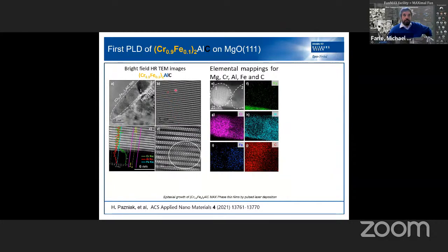So you see here a cross-section, again, beautiful lattice or atomic columns, nice structuring as expected from theory. You see here the element-specific scan for chromium, aluminum, iron. So you see here chromium oscillating as it should, aluminum oscillating as it should, and iron also oscillating as it should. So we can identify also here where chromium and aluminum, with lower resolution, are located. And here you see the trick.